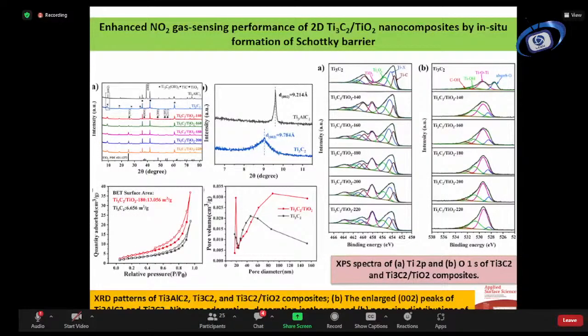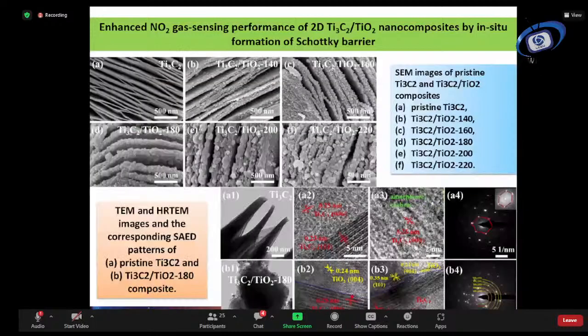So I will just go to the material formation. These are scanning electron microscope and transmission electron microscope images at different temperatures, for different samples. For example, in figure A, this is a simple MXene material, but then we dope it with titanium oxide. You can see in figures B, C, D, E, and F, they have been embedded very efficiently, very prominently, and uniformly as well. And then they produce a heterojunction between Ti3C2 and TiO2.